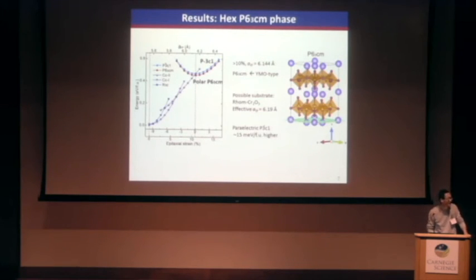Great. Okay, great. So have you thought at all about the chemistry of this system and whether or not there are stable vacancy ordering states nearby when you try to make this? So for example, this is a very large energy change from the perovskite, right? So do you start forming oxygen vacancies? Do you start forming mixed valence on the iron site? What happens? Have you thought about that at all? Shortly, no. Thank you.